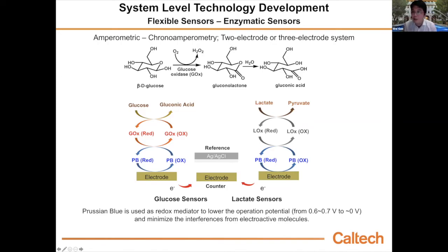Generation one detects hydrogen peroxide. We are actually using a generation two glucose sensor utilizing a redox mediator, Prussian blue. One of the major reasons we use Prussian blue is that we can operate the glucose sensor at a very low voltage. If we want to detect hydrogen peroxide based on a generation one glucose sensor, we need to apply very high voltage, like 0.6, 0.7 volt. But in a generation two glucose sensor, using Prussian blue as a redox mediator, we can operate the sensor at around 0 volt, which can minimize the influence from other electroactive molecules.